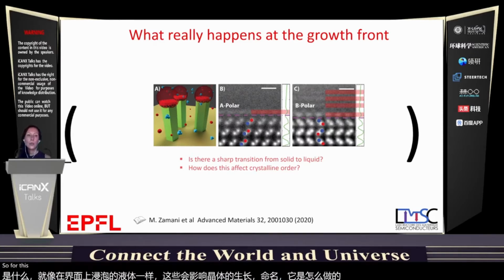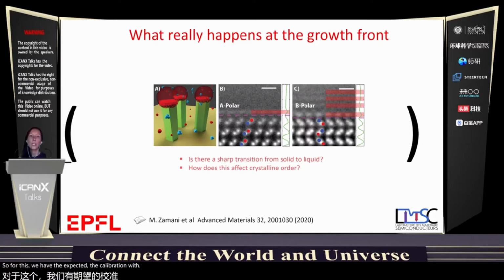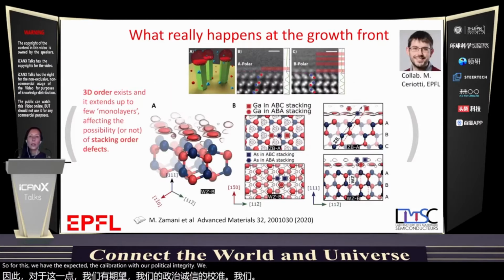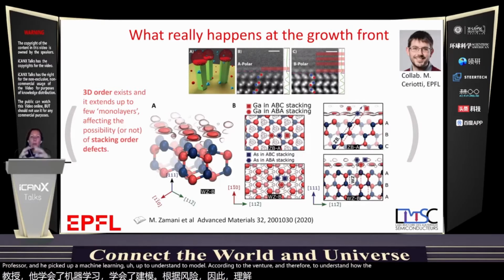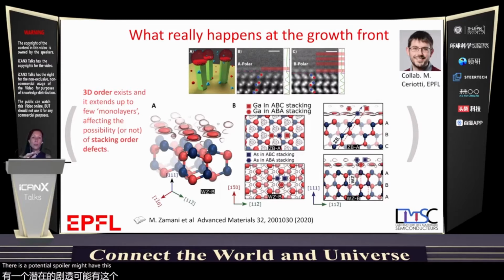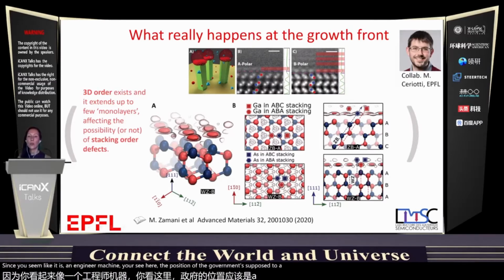So for this, we started a collaboration with our colleague Michele Ceriotti, who is a fully theoretical professor, and he did machine learning to model the gallium potential, and therefore to understand how the potential of gallium atoms is perturbed in the liquid state when it's close to a solid. He simulated this, and then here you see the position of the gallium atoms close to a surface of gallium arsenide.